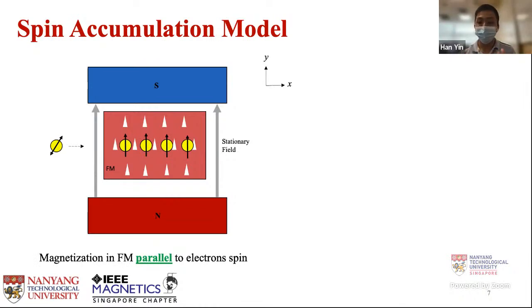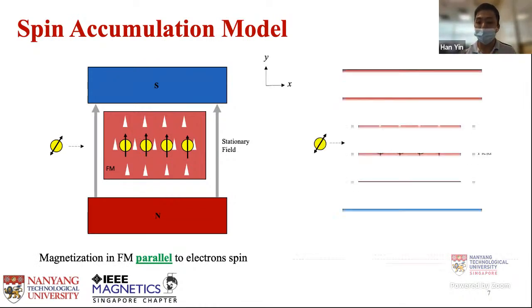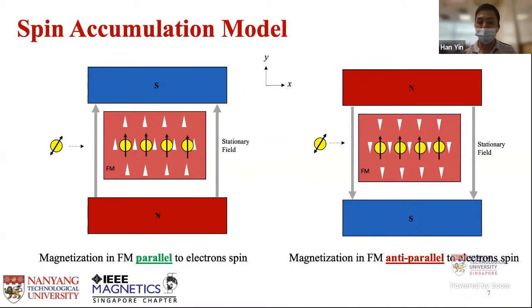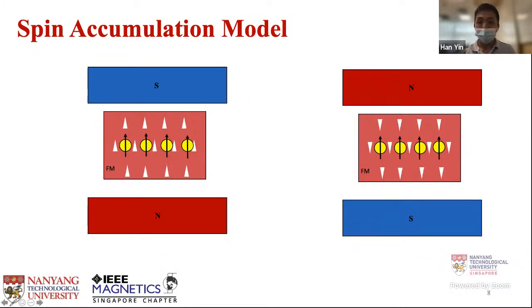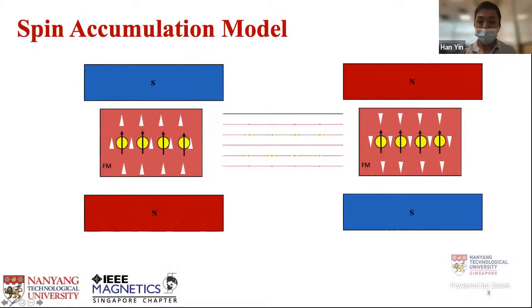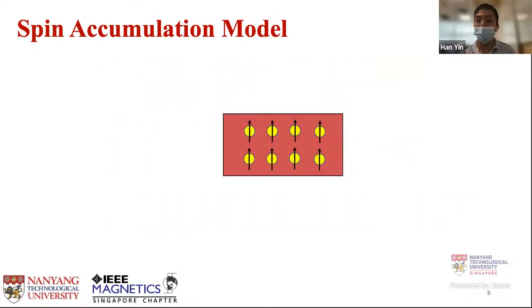Considering the other case, if we have a stationary field pointing down, the ferromagnet will follow the stationary field. The electron spin will still be pointing the same way, since the spin only depends on the direction in which we inject the current. The magnetization is anti-parallel to the electron spin, therefore we can expect to see a decrease in Hall voltage. So if we combine these two results together, we can isolate the signal purely for spin accumulation, since the FM magnetization contribution will be cancelled out.